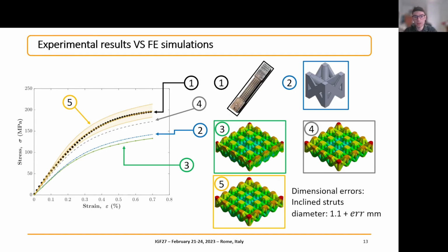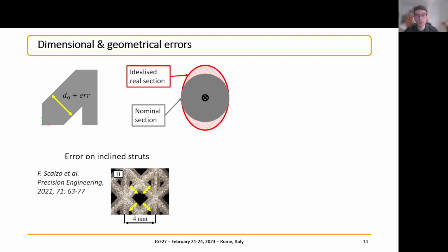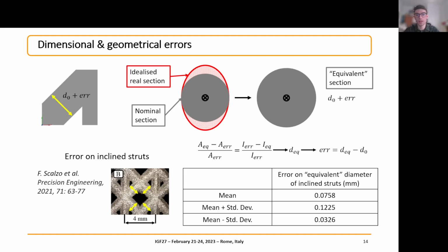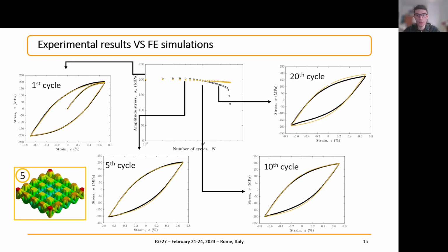but the best results were obtained including the dimensional errors in the model introduced by the manufacturing process, which is case number 5. So just to explain what I mean by dimensional errors, in brief, we observed that the inclined struts had an almost elliptical section, and the dimension in one of the axes was bigger than the nominal diameter. So we measured this deviation and then we made an approximated correction. Basically we maintained the circular section and calculated an equivalent diameter based on that error. With that adjustment, we also carried out a cyclic simulation of the structure, and as you can see, the cycles are well represented despite some small deviation in the last cycles due to the onset of the fracture.